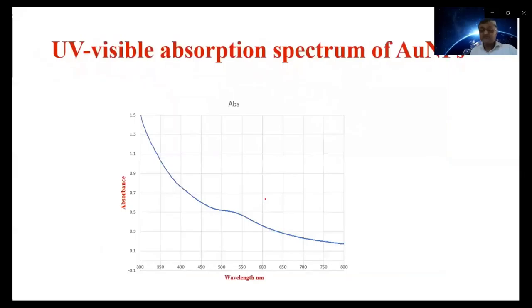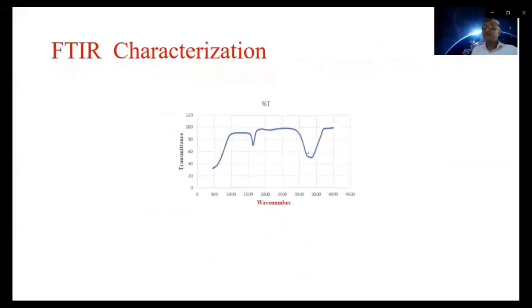Now, UV-visible absorption spectroscopy is suitable for confirmation of the formed gold nanoparticles. Here we have seen that the SPR peak appeared at 518 nanometer, and that confirmed the formation of the gold nanoparticles. Here we have a single peak, and that indicates the formed gold nanoparticles are spherical in nature. Now here, FTIR spectroscopy was done to find out the potential biomolecules present in the solution for the reduction and stabilization of gold nanoparticles.